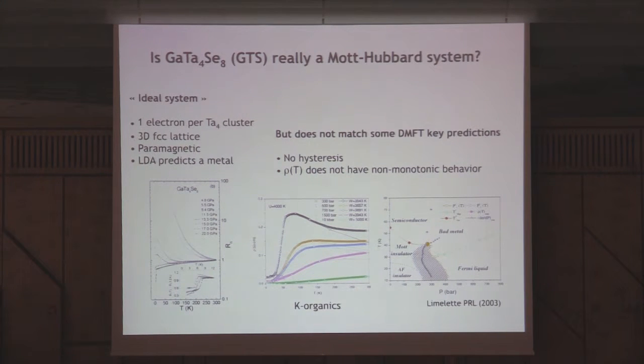So now, since we are DMFT people, we look at this and I said, is this oversold? I mean, is this really a Mott-Hubbard system? I have just tried to convince you that it's as good a Mott insulating system as it could be. There is no antiferromagnetism. It's 3D. It has an FCC structure, so it's fully frustrated with high connectivity, because the FCC lattice has a connectivity of 12, I think. So this is why I think these systems are like dream systems to test the dynamical mean field theory predictions.